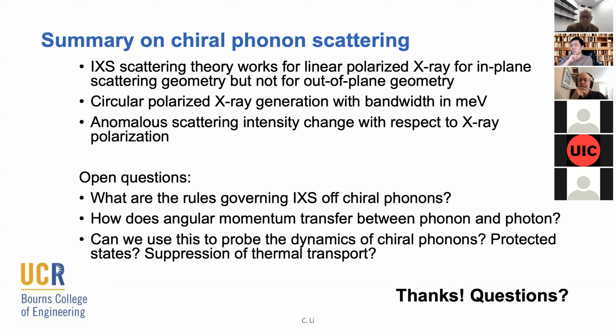And also you can see the optical phonons are relatively high in energy, so they don't couple readily. We're actually looking into some other systems where the optical and acoustic phonons partially overlap. The hope is there might be more interaction so we can extract a reasonable lifetime out of those. But on the other hand, IXS actually doesn't have good energy resolution to probe a phonon lifetime, so we are only giving an upper limit, I would say. So it could be the phonons are reasonably scattered, but just not as broad as some of the other ones. Okay, thanks.